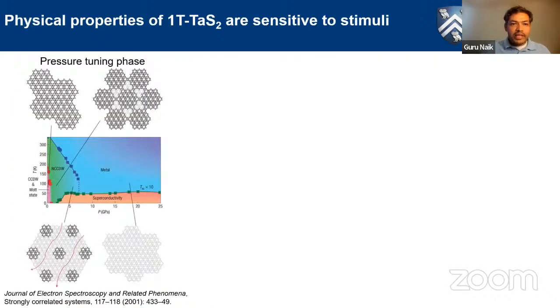Because of room temperature charge density wave interaction, this material has caught a lot of attention in recent days. It has been shown to exhibit tunable electrical properties. Here, for example, just with pressure, they have shown that you can get superconductivity to come up in this material. So superconductivity and charge density waves compete. They come from the same interactions and they compete. In just tantalum disulfide, superconductivity doesn't show up only because charge density waves are dominant. But pressure can suppress charge density wave interaction and bring superconductivity up.